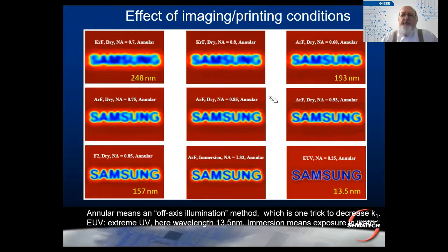Anyway, I did also have, deep in my Sematech stuff, this physical description that sort of shows you where we're coming from. 248 is our quarter micron or micron type of resolution. As you can see here, it's not all that good. Notice the numerical aperture of 0.7. As we go to 193, which is an argon fluoride laser, numerical aperture stays about 0.7. I think you can visibly see quite a bit of improvement of resolution. The big competitors 15 years ago were a fluorine laser, which gave out 157, and a markedly good numerical aperture. So you can see here pretty good performance.